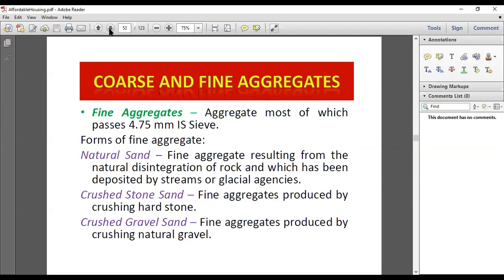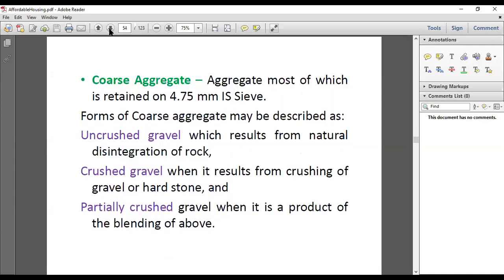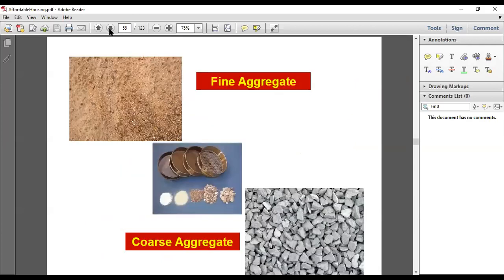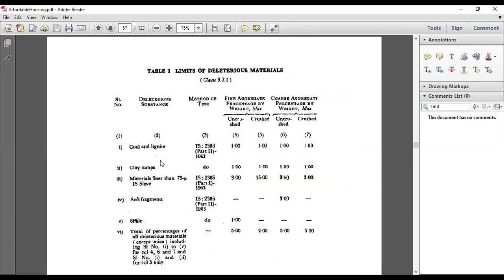Now, one of the big problems is your aggregate. You know that in concrete, 70% is your coarse and fine aggregate, but we never do testing in a proper way. So sieve analysis is a must for this, and by sieve analysis you will know the gradation. Because if there is not full gradation, then there will be voids, and there will be water absorption, acid ingress in the concrete, and it is going to reduce the strength of the concrete. So that's why, many times there are deleterious materials. Coal is there, clay is there, soil is there, but people don't remove it.